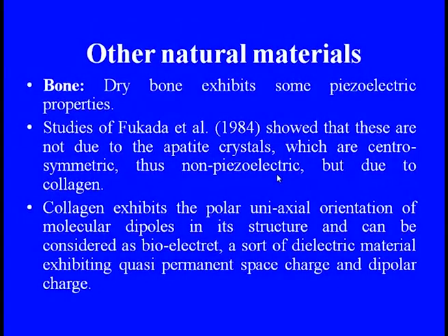Even we can go with other natural materials like bone. Dry bone can sometimes exhibit a similar piezoelectric effect. Fukada et al. in 1984 showed in their studies that this is not due to the apatite crystals, which are centrosymmetric and non-piezoelectric, but due to collagen, which exhibits a polar uniaxial orientation of molecular dipoles in its structure and can be considered a bioelectret, a sort of dielectric material, exhibiting quasi-permanent space charges and dipole charges.